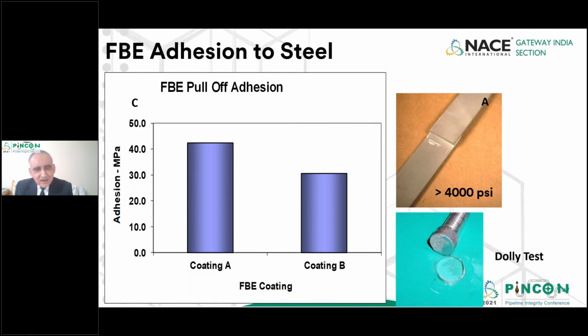So again, the value of pulling force can be measured either in psi or in megapascal. Some equipment will measure in psi, so anything above 4000 psi is a good adhesion. Or if we measure the data in terms of megapascal, it should be at least 30 to 40 megapascal. So that's a very, very high level of adhesion for FBE. So tender documents normally recommend that when a single layer pipe is coated, this pull-off adhesion test be performed.